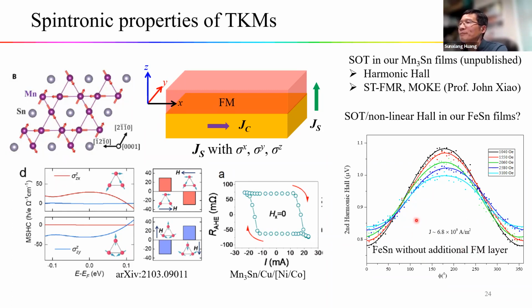So we use a lock-in. This is just a second harmonic signal from the anomalous Hall voltage, in the planar Hall geometry. So the field is in the plane. Oh, okay, I see. That's why you have angular dependence. Yeah. If you do the second harmonic on, let's say, platinum cobalt platinum, you also see something similar. But for this sample, we don't have an additional ferromagnetic layer.